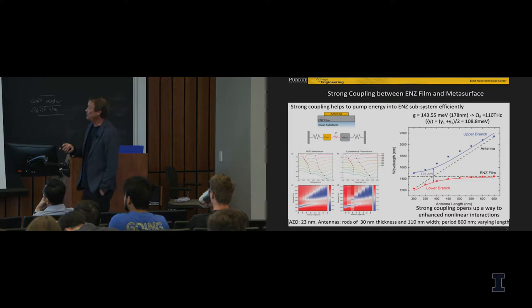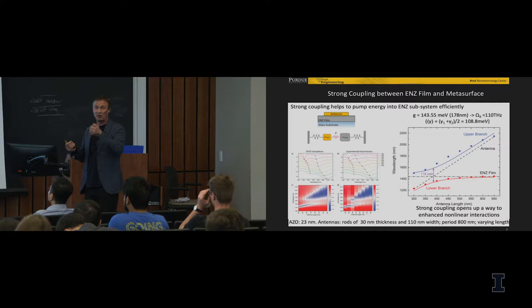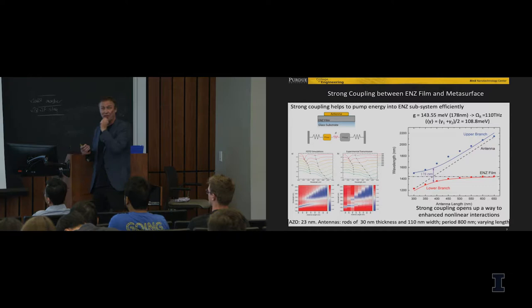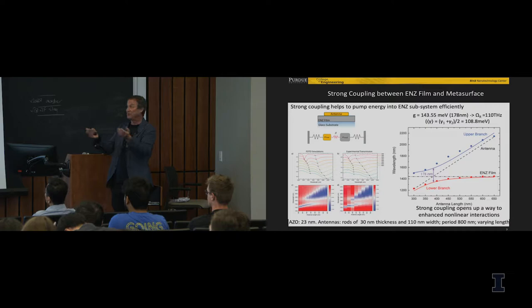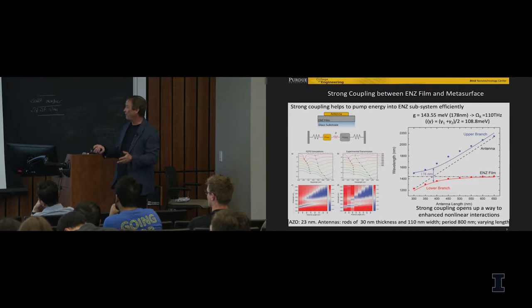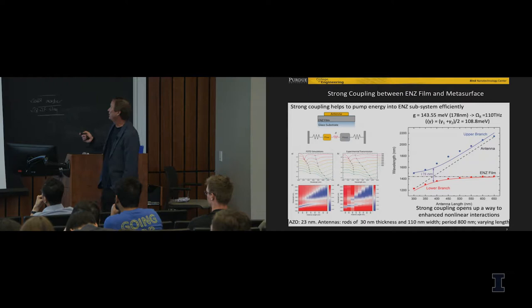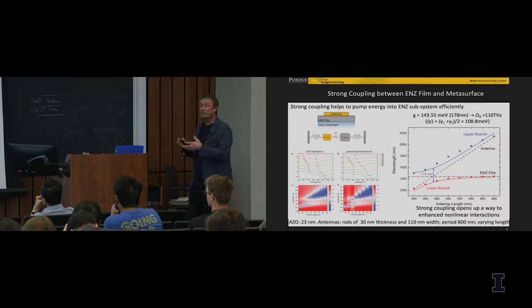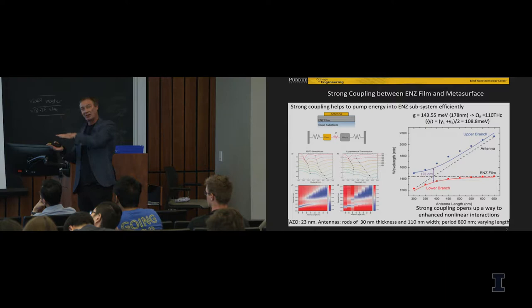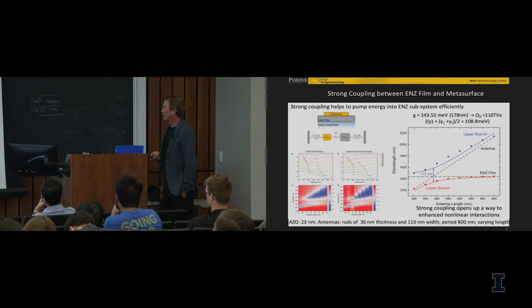So that's exactly what we did, and we showed that by using a simple model of coupled oscillators, one oscillator representing the ENZ mode, the mode for the frequency where epsilon crosses zero, another representing the frequency of these antennas, and we make them the same. Then you see that there is really this fork-like behavior, basically like a repulsion, if you wish, between these two modes. And what we see is that the splitting between the modes caused by this coupling actually exceeds the rates of both plasmonic decay, because these antennas are plasmonic, and the decay of the ENZ mode, which means it's a strong coupling. Basically, there is a strong coupling between the metasurface and the ENZ substrate. And because of that, we eventually are able to pump energy effectively into the ENZ.